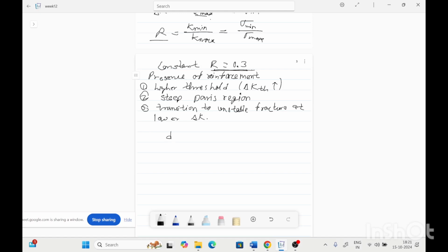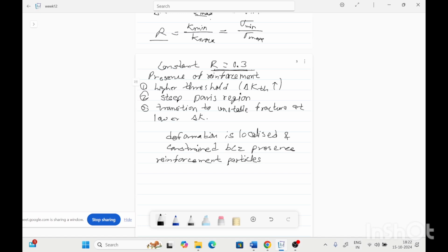Means the deformation is localized and constrained because of the presence of the reinforcement particles. So because of this, the deformation will be non-uniform, so that leads to the unstable fracture, and the fracture will also be at a lower delta K value.